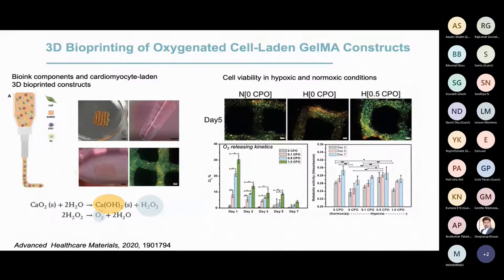Now, one of the other things that I mentioned is that you can make inks that release oxygen. So we've made these bioinks that release oxygen by having materials like calcium peroxide that can be used to generate hydrogen peroxide and subsequently oxygen and water. And we've shown that these inks can be used to maintain cell viability. So normally, as you can see here, this is a normoxic condition. You can see the cells remain viable in green. In hypoxic condition, there are a lot more dead cells, as shown in red. And once you have the calcium peroxide, then the cells remain more viable.